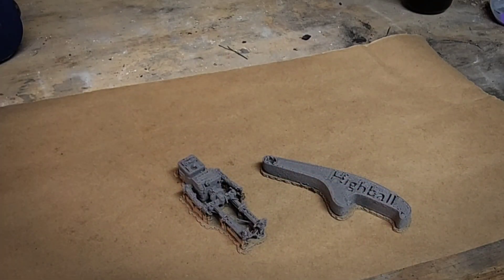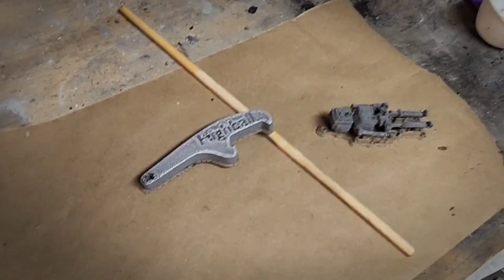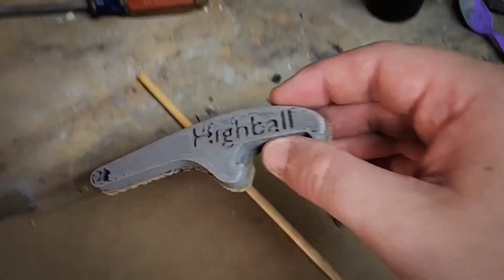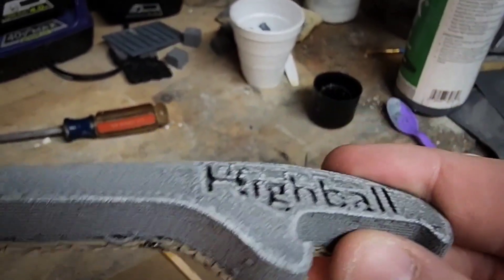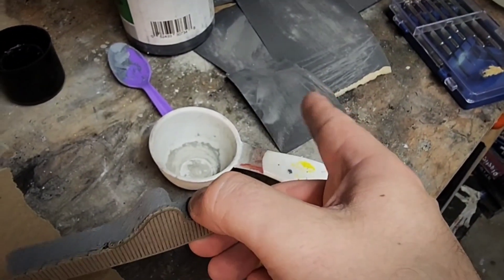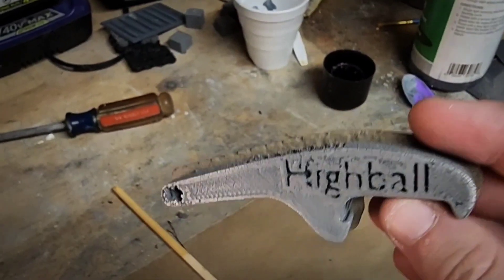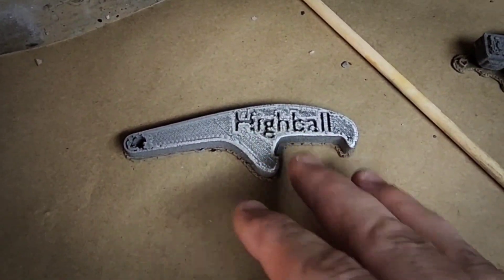Overall, very happy with this improvement and I hope to see this come out of beta. I actually thought I was done with the review, but my robot actually fell off and I noticed something very interesting — this beta filament polishes incredibly easily. I simply did a little scraping with sandpaper for about 15 seconds and I already have a metallic sheen. So for anyone looking for a very easy 3D printed cosplay metal-looking part — I mean, it is metal, it's just not the strength until it's sintered — if you're looking for the visual aesthetic, this might also come in very handy.